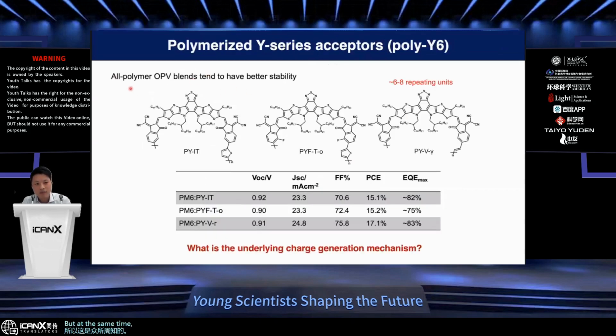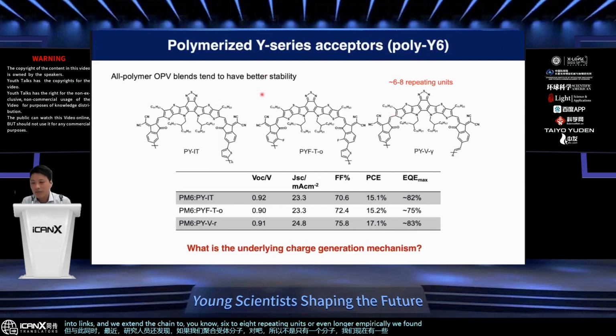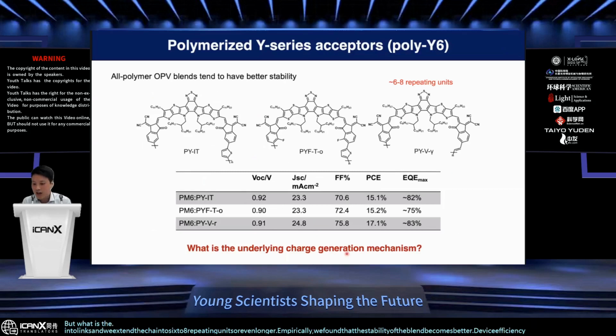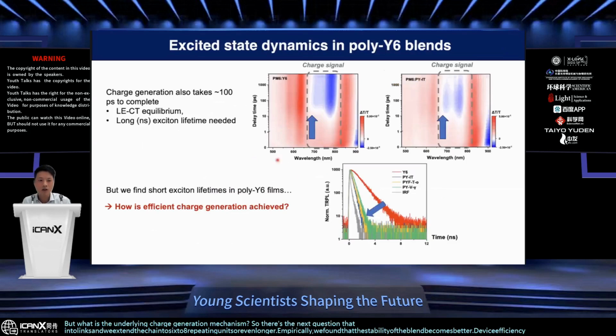But at the same time, recently, researchers have also found that if we polymerize the acceptor molecule, so instead of just having one molecule, we now have some interlinks, and we extend the chain to 6 to 8 repeating units or even longer, empirically, we found that the stability of the blend becomes better. Device efficiency becomes better. But what is the underlying charge generation mechanism? So that's the next question that we try to solve.